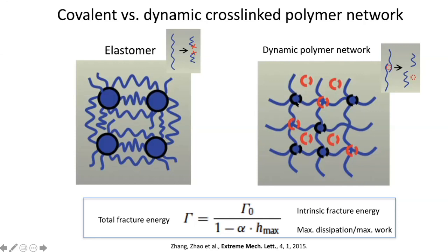In certain polymer design, dynamic bonds may form simultaneously when others are breaking to replenish them. Incorporating such an energy dissipation mechanism in addition to other ones, such as chain elongation, alignment, and crystal breakage, allows polymer network to gain a larger fracture energy and sustain a larger strain before damage.